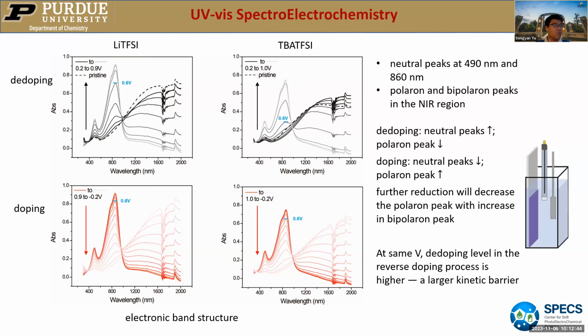When we de-dope the polymer, the neutral peak at 860 will increase, and also the small peak at 490, and the polaron peak will decrease. When we dope the polymer, the bipolaron peak will increase. And if we further reduce the polymer, the polaron peak will decrease with the bipolaron peak increasing. So that is how the electronic band structure looks.